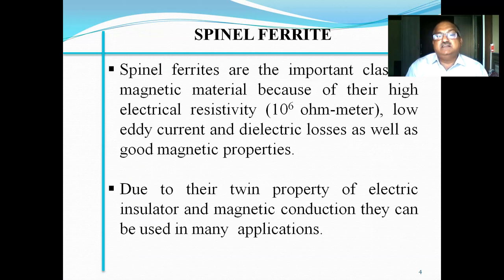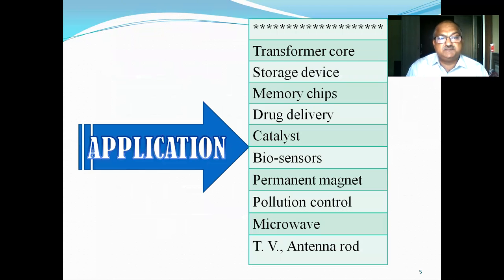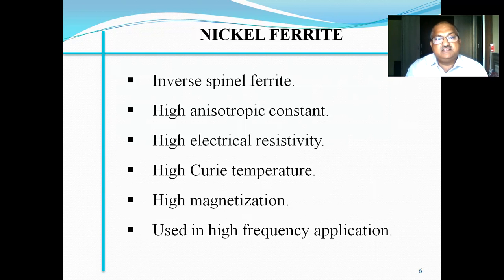Spinel ferrites are an important class of magnetic materials because they have high electrical resistivity, low eddy current as well as dielectric losses, and good magnetic properties. Due to their twin property of electrical insulator and magnetic conduction, they can be used in many applications. These are the applications of spinel ferrites. Nickel ferrite is an inverse spinel ferrite with a high anisotropy constant, high electrical resistivity, high Curie temperature, and high magnetization, used as